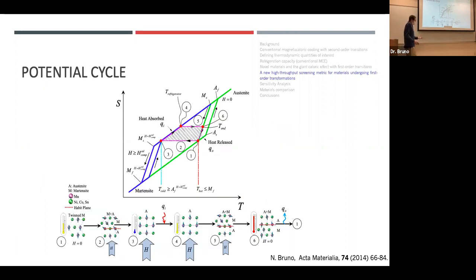So if we wanted to use the material in a refrigeration cycle, we need to start at this martensite finish temperature. This is an entropy versus temperature diagram. In field is the blue curve, out of field is the green curve. We get a decrease in those transformation temperatures.